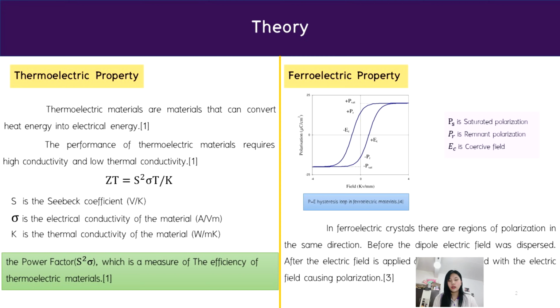thermoelectric material. Ferroelectric property. You can see the hysteresis loop in ferroelectric material, and PS is saturated polarization, PR is remnant polarization, and EC is coercive field. In a ferroelectric crystal, there are regions of polarization in different directions before the electric field is applied, so the dipoles are dispersed. After the electric field is applied, dipoles are aligned with the electric field, causing polarization.